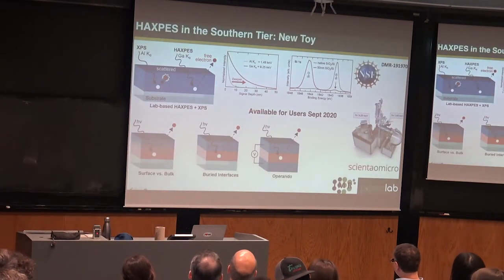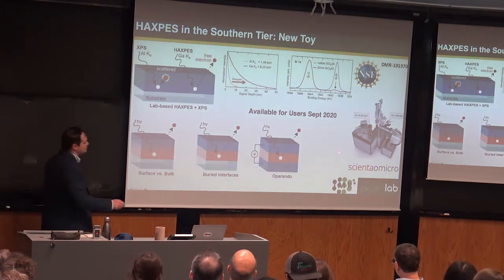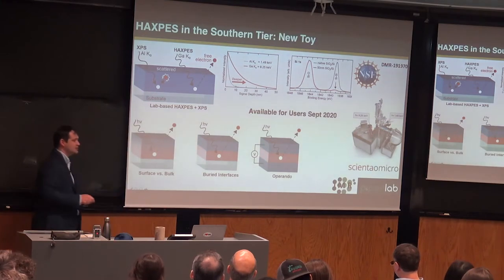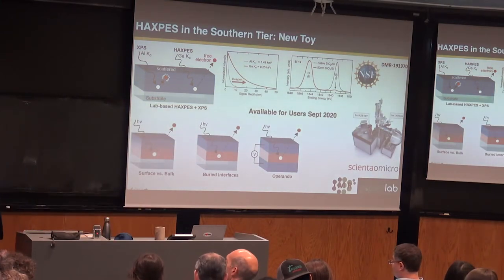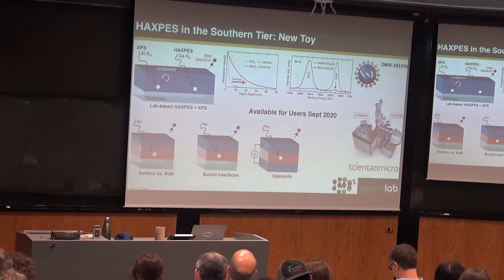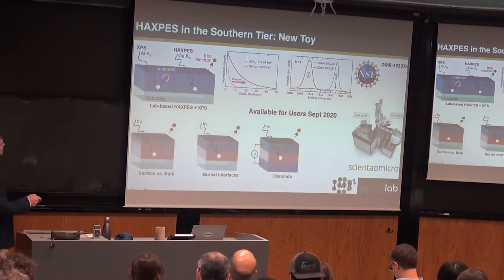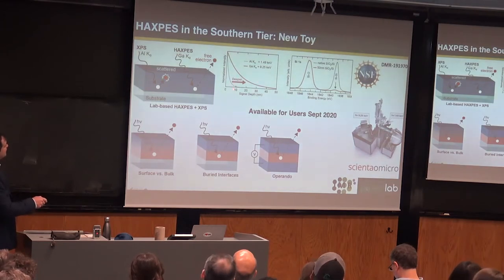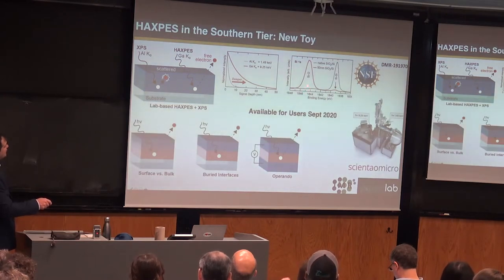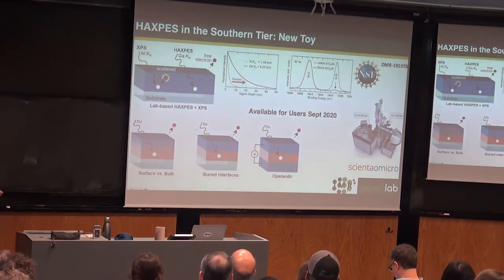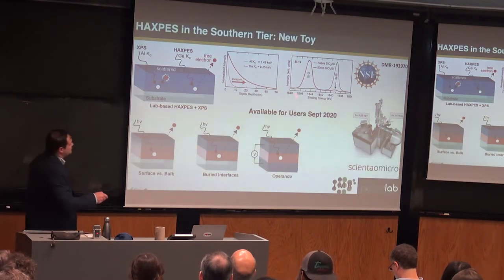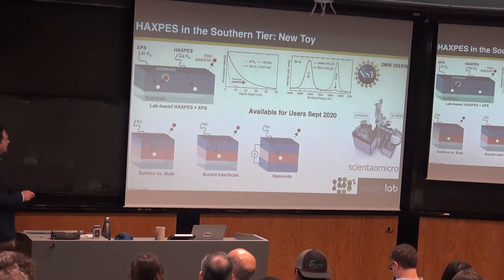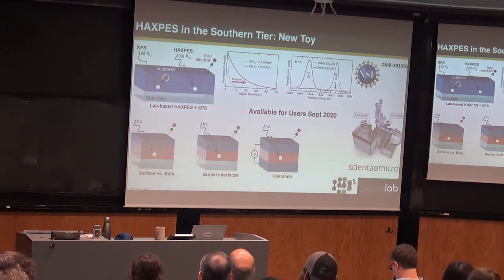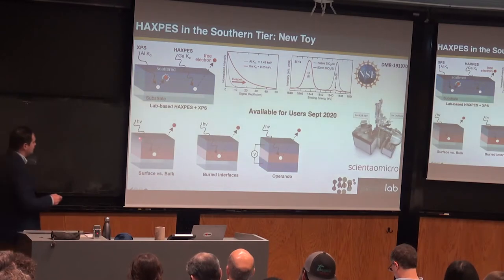But fortunately, we've recently had advances where we can use a liquid gallium jet source and get comparable performance in the valence band. Comparable performance is what is possible at some synchrotrons, others may be better. We can now use a liquid gallium K alpha source, and so we can actually see core level silicon spectra underneath 50 nanometers of silicon oxide. And so the increased ability to get information deeper within means that we can distinguish things where there are pronounced differences between surface and bulk, so we get a better indication of what the true interior of the material is.